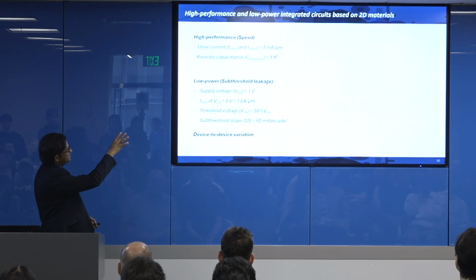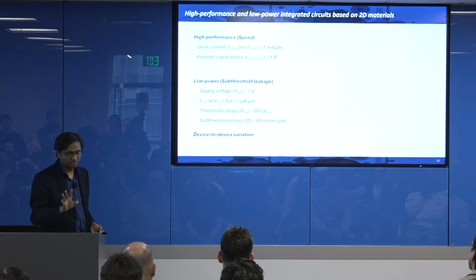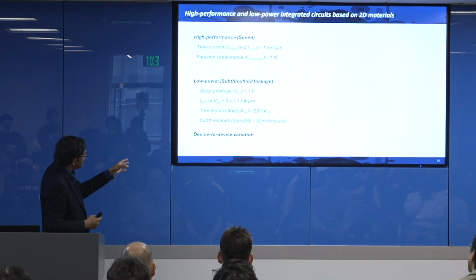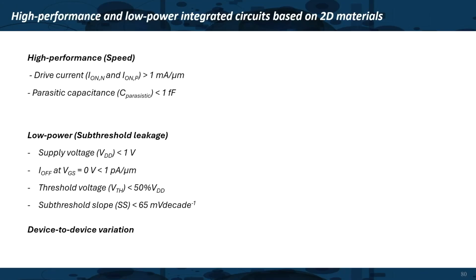So you can see that the requirement for the high performance devices is that you need to have more than a milliamp per micrometer on-state current from both N and P, and your parasitic capacitance has to be low, because parasitic capacitance has been an understudied topic in the 2D community. And one more important thing is that low power application requires your supply voltage to be less than 1 volt. Your off current has to be 0 or low at Vg equal to 0, and that is something not really addressed in the 2D community.